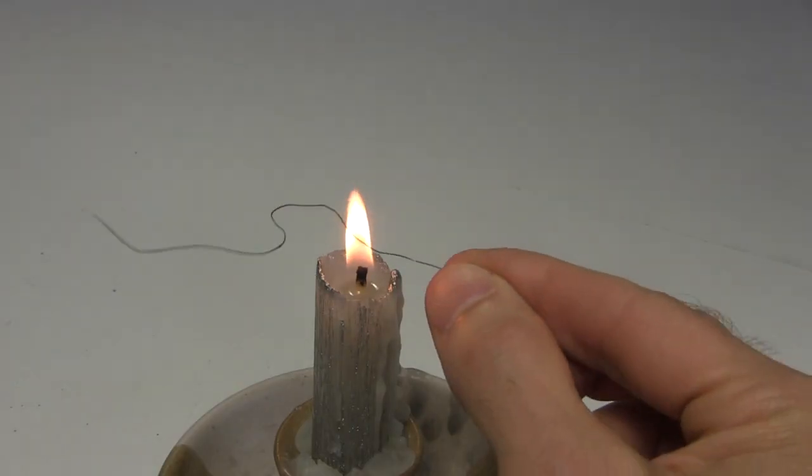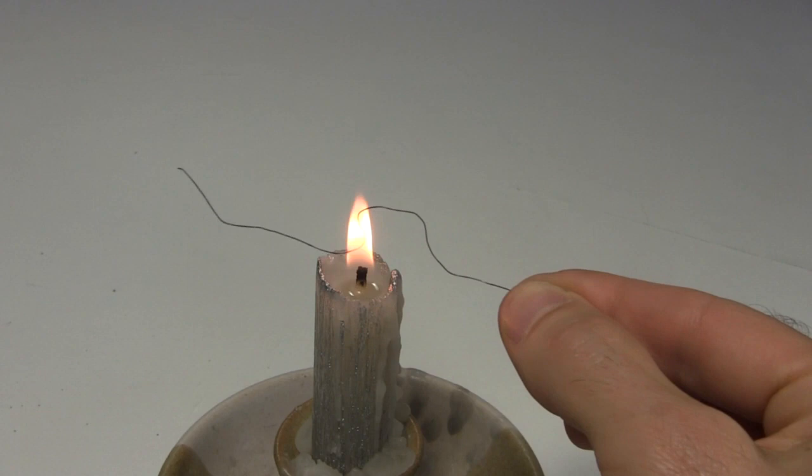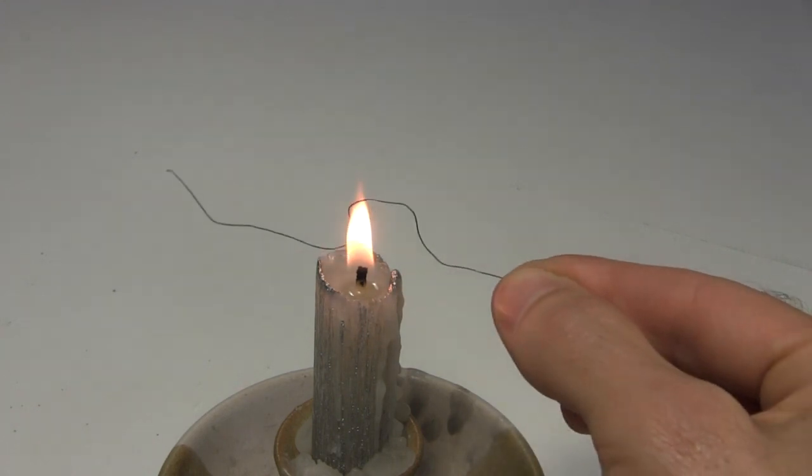But be careful doing it this way. If you leave it in too long, like I'm doing here, then it reprograms it for whatever shape it happens to be in at the time.